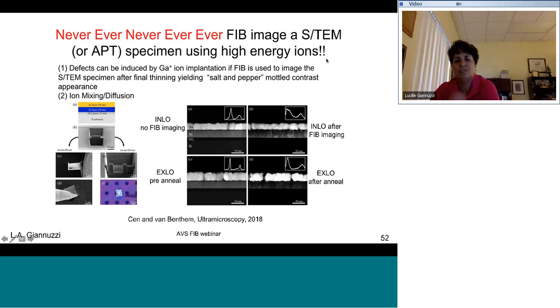So as I said before, never, ever, ever FIB image a S/TEM or atom probe specimen using high-energy ions. And this is an example showing what can happen if you do this in-situ experimentation using in-situ lift-out versus ex-situ lift-out. Because by virtue of doing in-situ lift-out, you inevitably have to turn on the ion beam at some point to be able to see what you're doing to get the sample down to the MEMS device, whereas this is not the case with ex-situ lift-out.